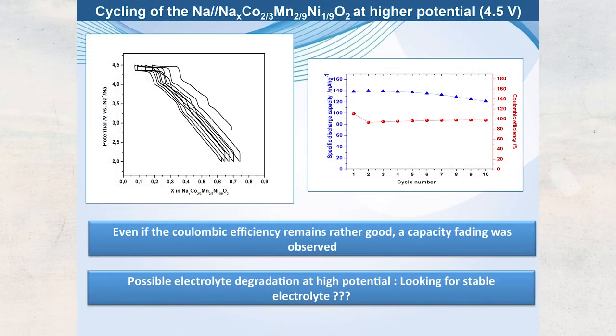When cycling up to 4.5 V, we observe a plateau revealing electrolyte decomposition problems. We get much more capacity — around 140 mAh/g, similar to the lithium analogue — and high efficiency, but the cyclability is poor. Our current work focuses on understanding what happens at this high voltage.